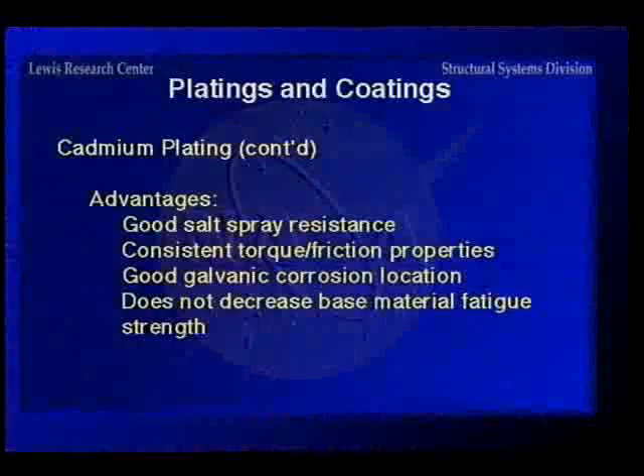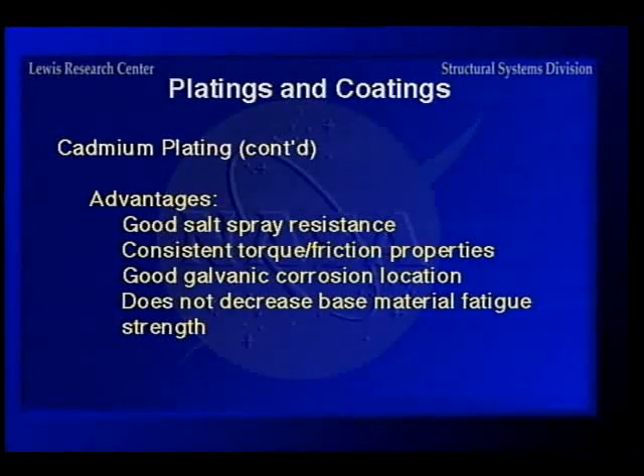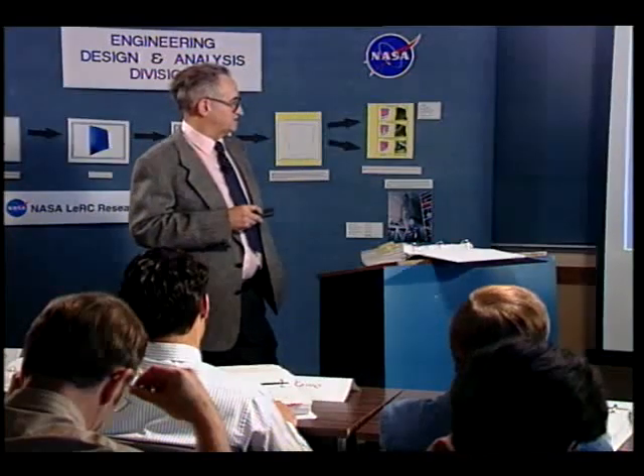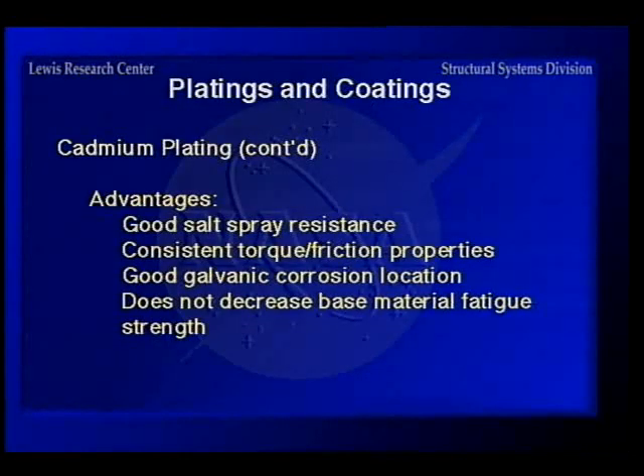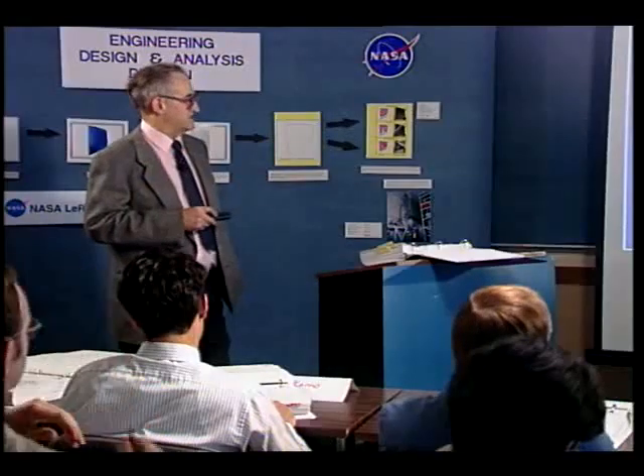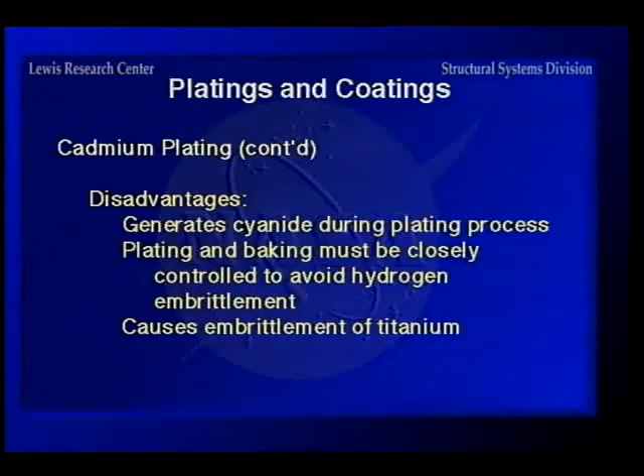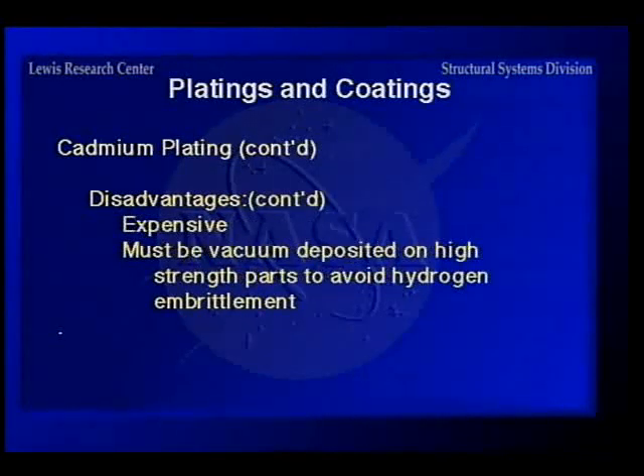Now, the advantages of cadmium: it's good salt spray resistance, so it's very good in marine environment for airplanes where they're exposed to salt all the time in the winter time. It's consistent on the torque friction properties. It has a good galvanic corrosion location, and it doesn't decrease the base material fatigue strength. But the disadvantages: it generates cyanide during the plating process, which is nasty stuff that the EPA watches very closely. And of course, I mentioned the plating and baking has to be closely controlled to avoid hydrogen embrittlement. And it causes embrittlement of titanium. It's very expensive, and it has to be vacuum deposited on high-strength parts to avoid hydrogen embrittlement.